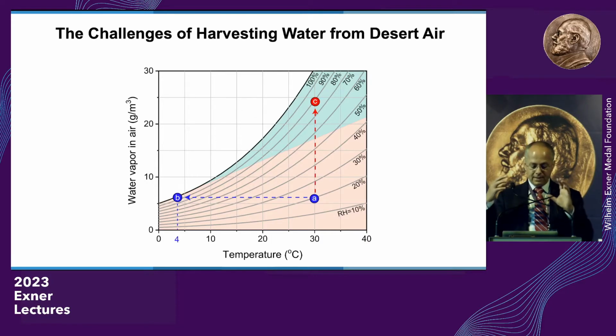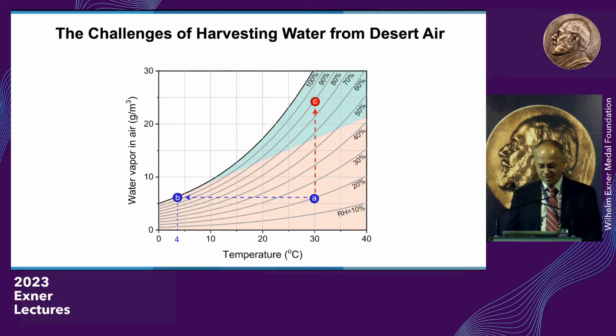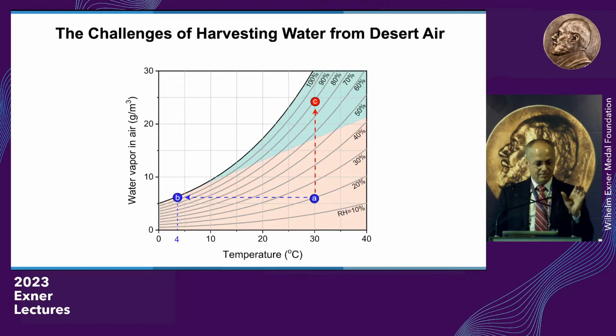However, if you have a MOF that takes in the water, then you concentrate the water in the pores of the MOF. I put that MOF in a box, close that box, and expose it to the sunlight. Now the water humidifies the box. So I've turned desert air into tropical air. Now my humidity is about 90% relative humidity. And to get that water out, make it drinking water or make it liquid water at 100% relative humidity, I have to only cool down by a few degrees Celsius. And that's the key to how the MOF will operate.